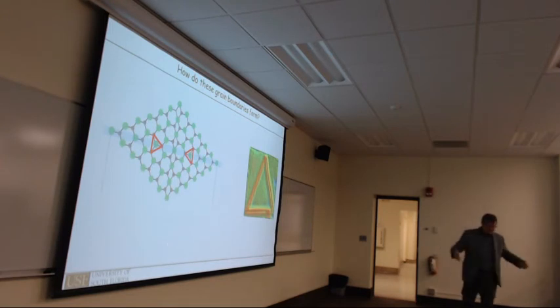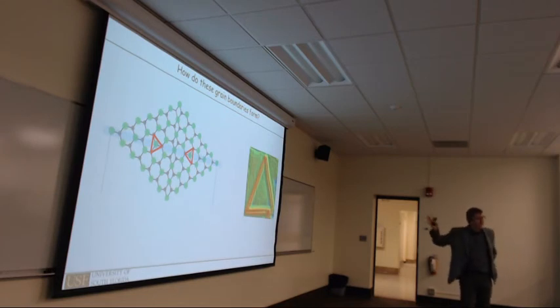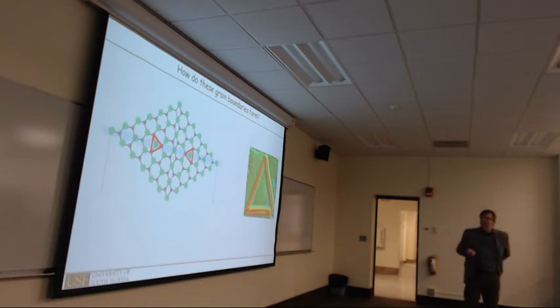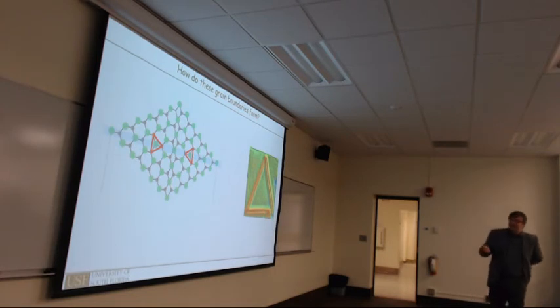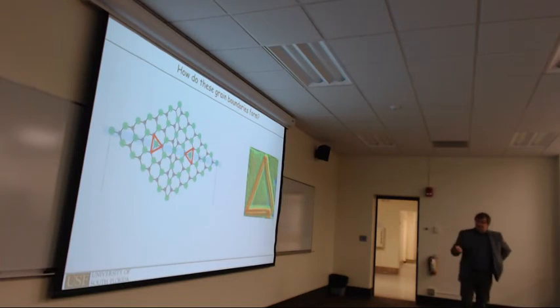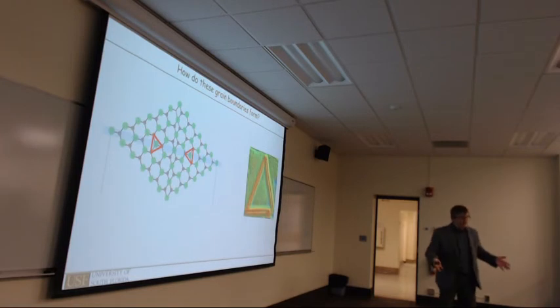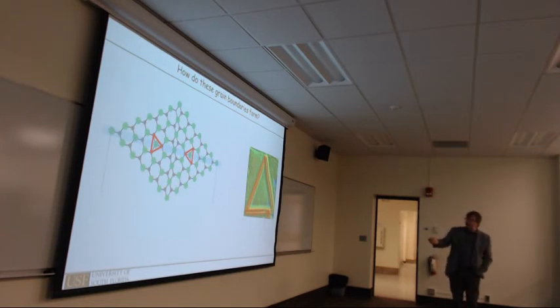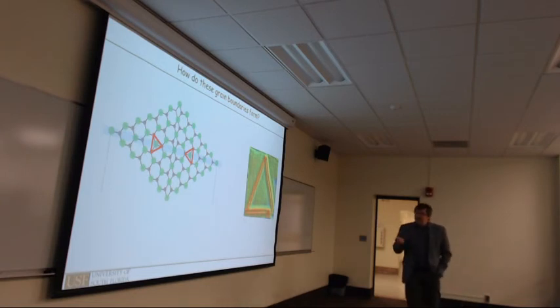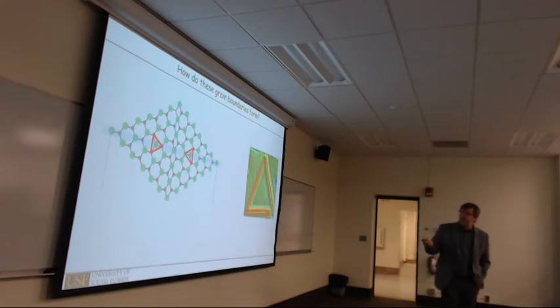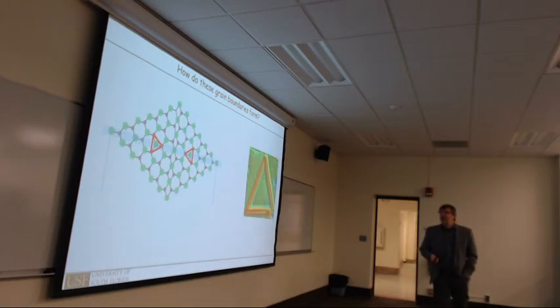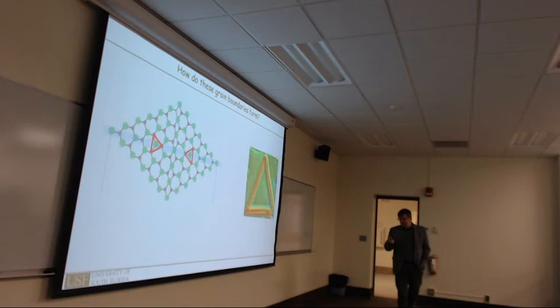Okay, so far I showed you these boundaries, and they have some interesting properties. We also showed that they may exhibit Tomonaga-Luttinger liquid, but I thought maybe that's not that interesting in the chemistry department. But what may be interesting is how these grain boundaries form. These are twin boundaries, and of course one assumption would be that we just nucleate twins, and then they grow together and form a grain boundary. Oftentimes we see just these triangular loops, which is a closed grain boundary, so you have a twin inside and a twin outside. Another thing I want to point out is that the gray balls are molybdenum, and the green balls are selenium. The grain boundary has a different stoichiometry. It's molybdenum 1, selenium 1, while the other one is molybdenum diselenide. So there's excess molybdenum in the grain boundary.